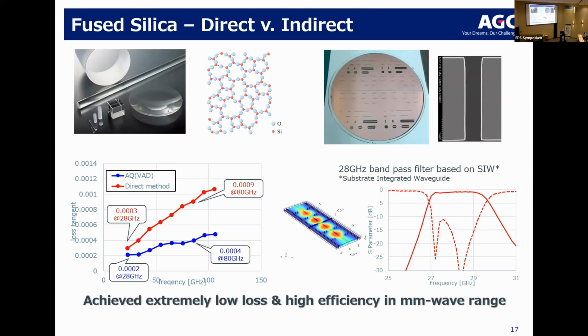As you can see, the dielectric constant and insertion loss is very, very low and stays very, very stable at the higher frequencies. And you can see that the bandpass filters here perform very well. The change in the slope of the line is controlled by the contaminants in the quartz itself. If you can control the contaminations in the quartz, you control loss. That's true for everything: glass, PCB, everything. The electron clouds actually dominate what causes loss.